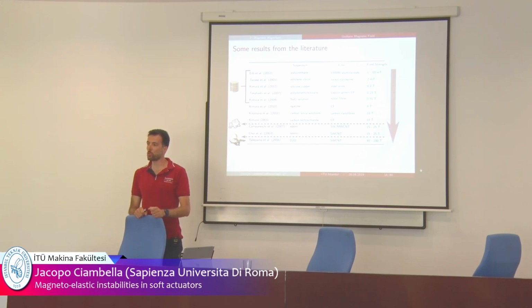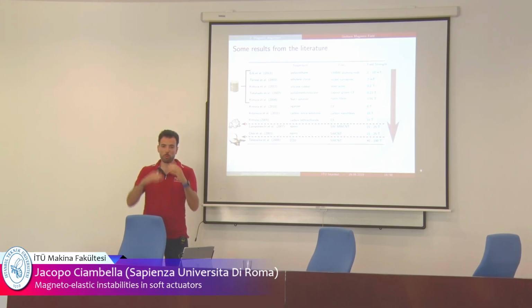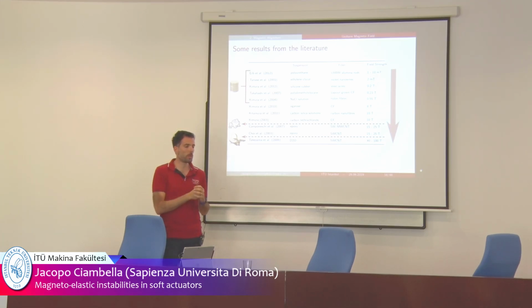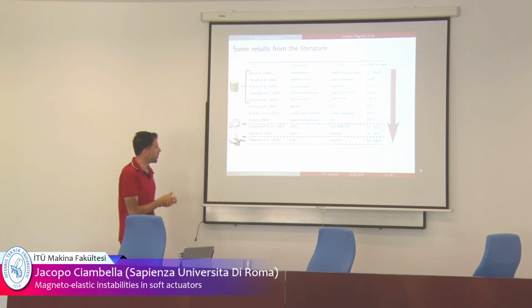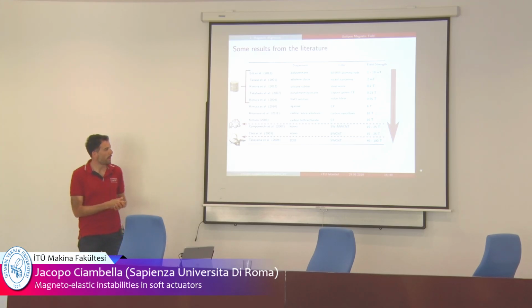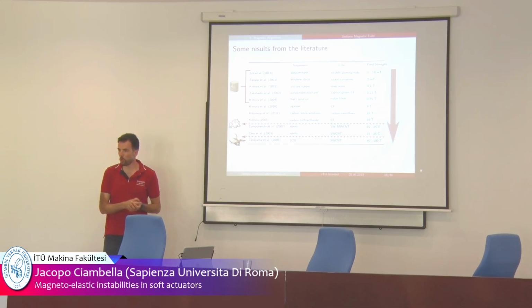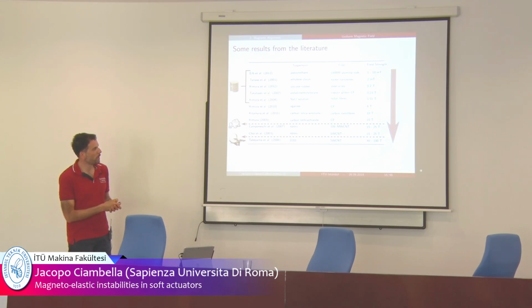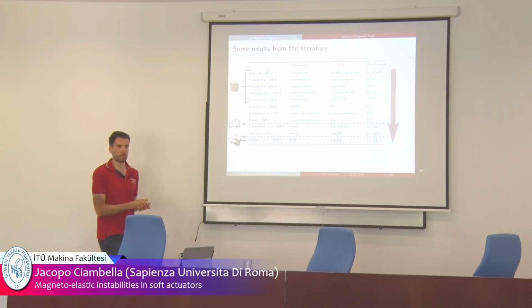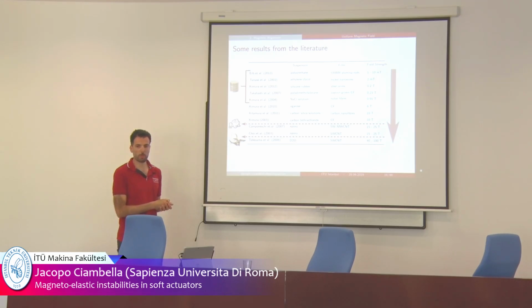In the experiment I showed you before, where they used a steel rod to obtain the bending of that beam, they used 8 Tesla. Then you can go over 10 Tesla; with 10 Tesla you can make a frog levitate, for instance. And with 40 Tesla... 25 Tesla is the MR machine. So huge fields. In all our experiments, we were well below that, 0.2 Tesla, okay, with our material. So a very simple experimental setup.